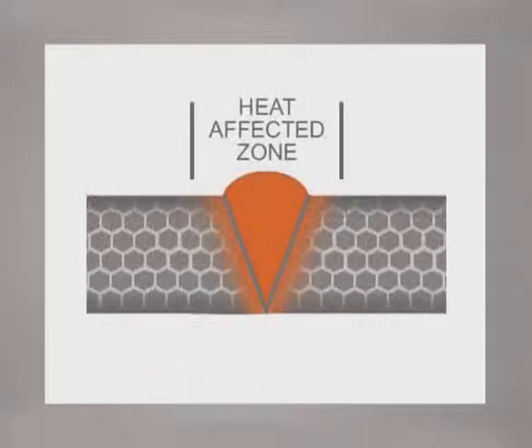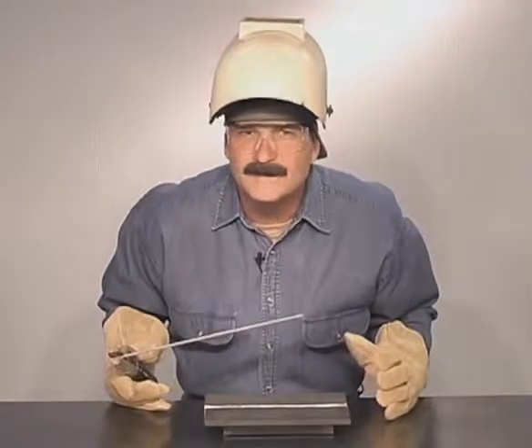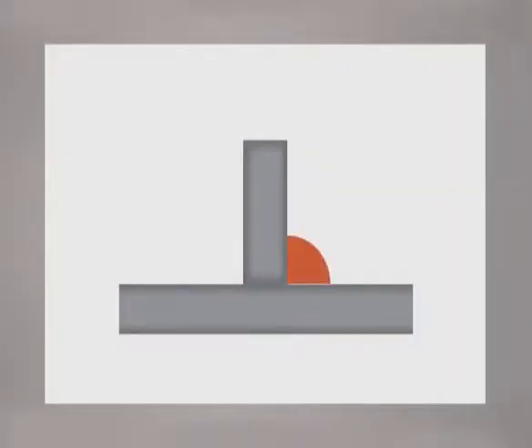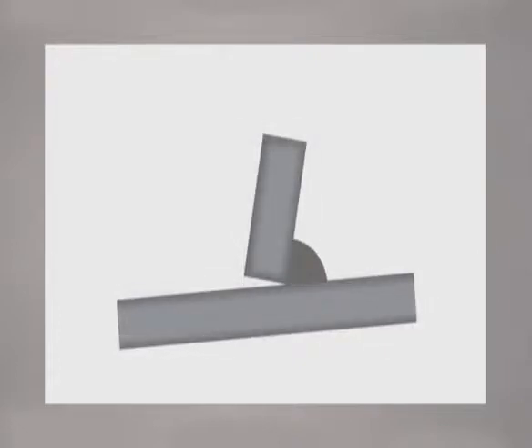In welding, the metal adjacent to the weld bead becomes hot enough to change the structure of the grains. Because only a relatively small area is heated, the metal cools quickly, forming smaller grains and becoming harder right alongside the weld. Welding also causes the pieces of metal in the joint to draw. Heated metal expands, so during the weld, the molten filler metal is deposited in its maximum expanded state. As it cools, it contracts. When the metal is free to move, it will draw in the direction of the weld.